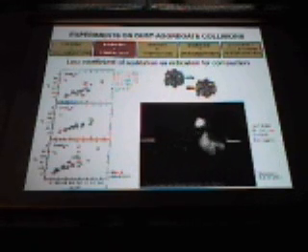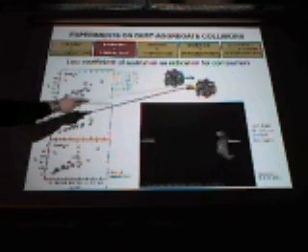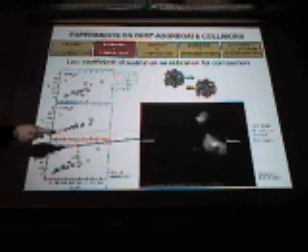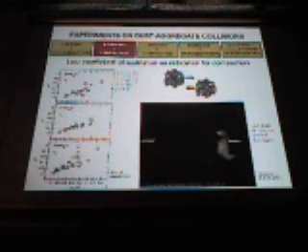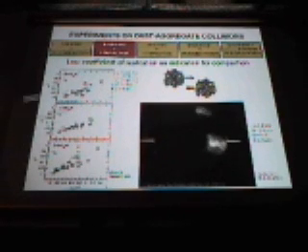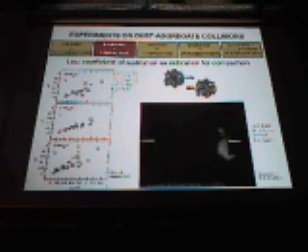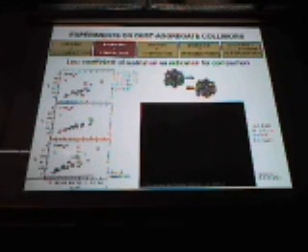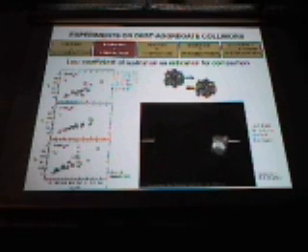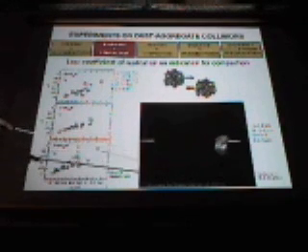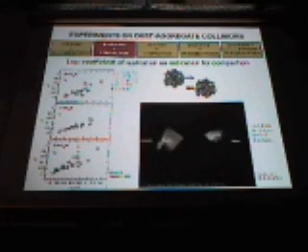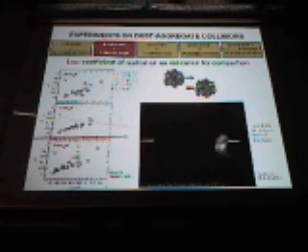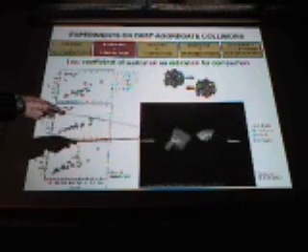So the second type of experiment is what you see here, or in the sketch. 2 aggregates. This time we cut out these aggregates by means of a razor blade from our dust cakes, the larger dust aggregates. So these are 3 to 5 millimeters in size. And they collide in a microgravity environment. So we went to a parabolic flight aircraft, built our experiment inside the aircraft, performed these collisions at 40 centimeters per second relative velocity in this microgravity environment, and what we see is the particles are rebounding at these velocities.